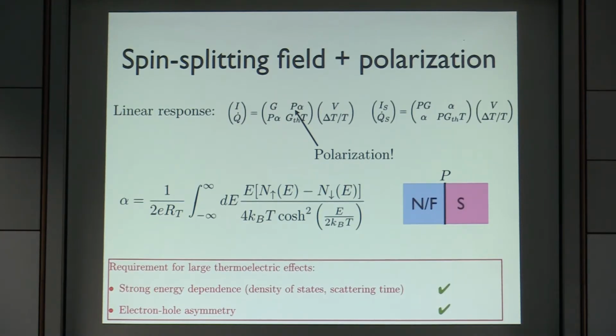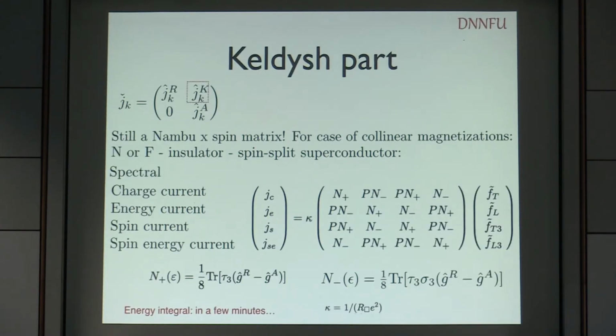Now we can simply calculate it. What we basically get is that the thermoelectric part of this matrix gets a prefactor of P, which is the polarization of the contact. And then this alpha here is related to the spin asymmetry of the density of states. So in this case we get strong energy dependence and electron-hole asymmetry. This is related to our theory, looking at the different currents. What I just described is basically this block connecting charge current and energy current together.